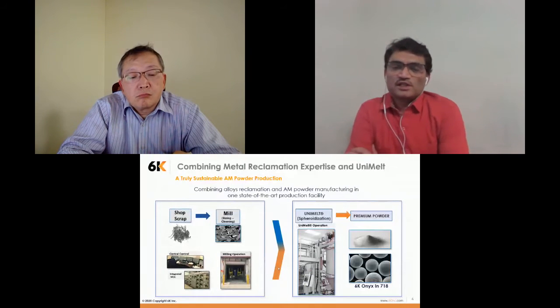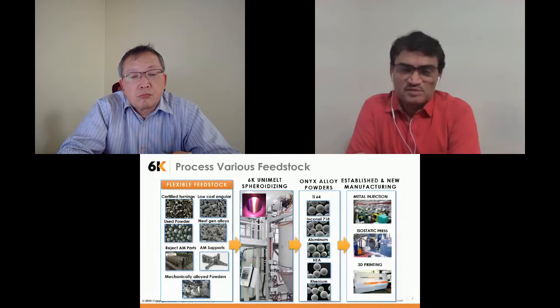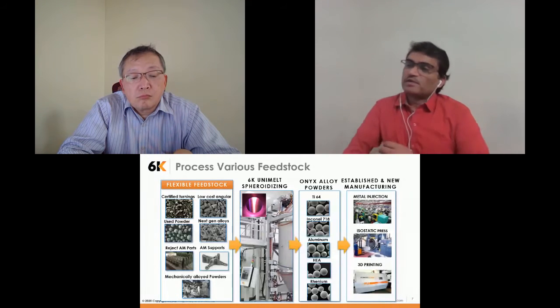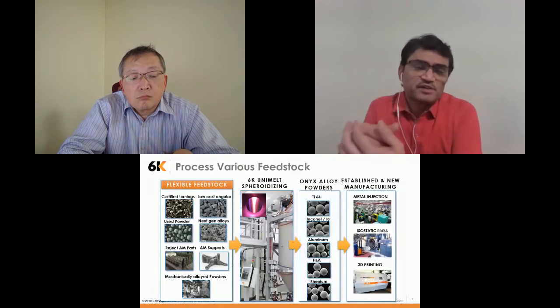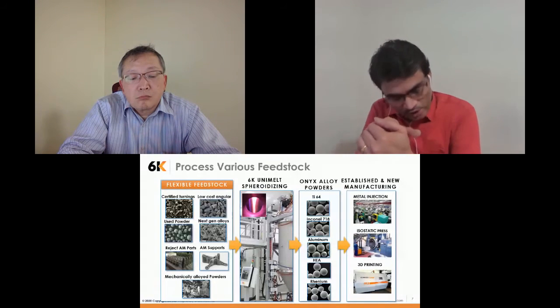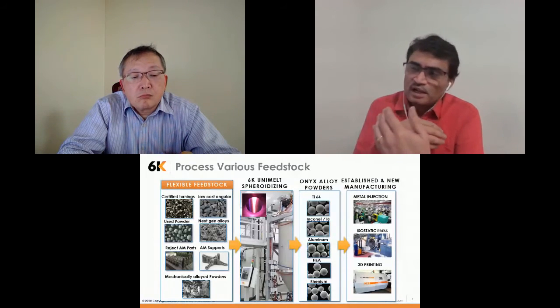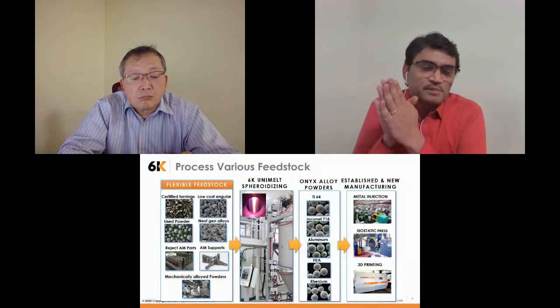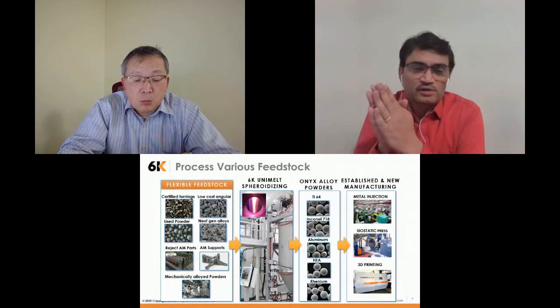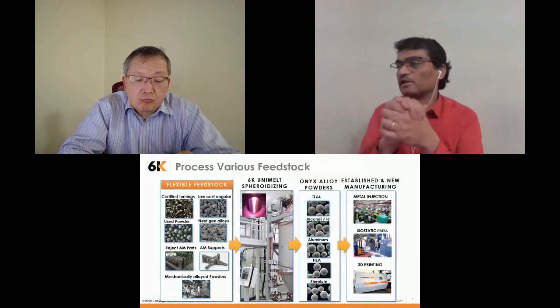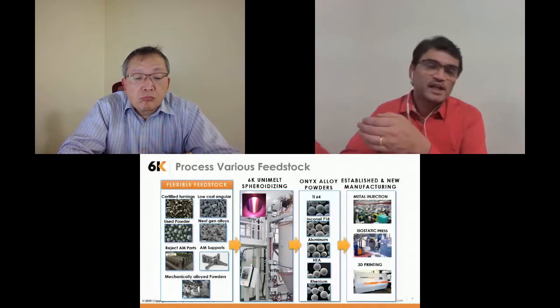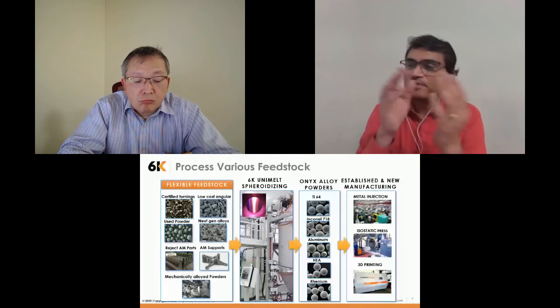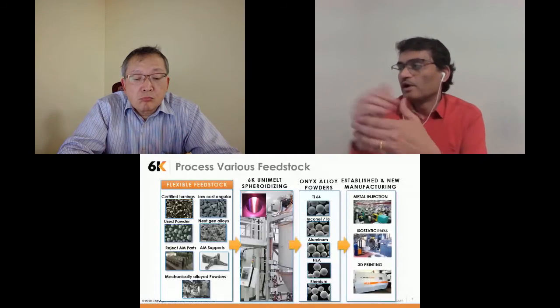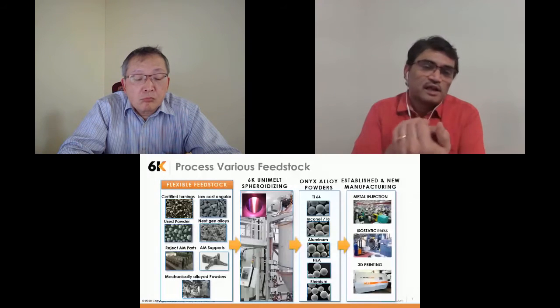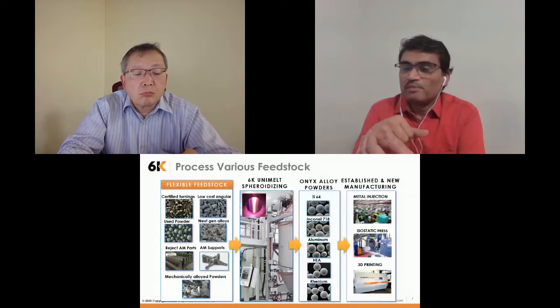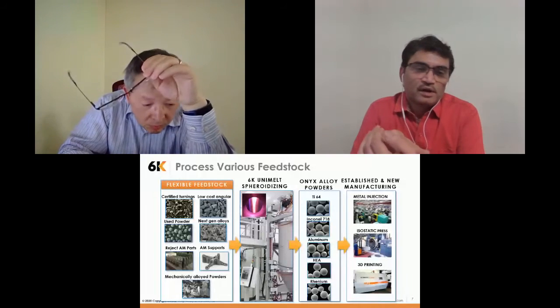And this is showing the capability of UniMelt handling different types of feedstocks, right from certified turnings to regular powder, even the used powders and the spongy powders. We can use different types of feedstock, and then we can produce different highly spherical powders. These are examples here that we have produced from different types of feedstock, like titanium 64, Inconel 718. And at the same time, we can use mechanically alloyed powders as a feedstock and produce high entropy alloys.